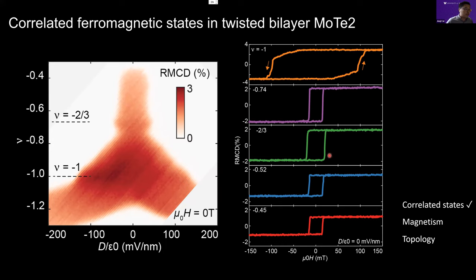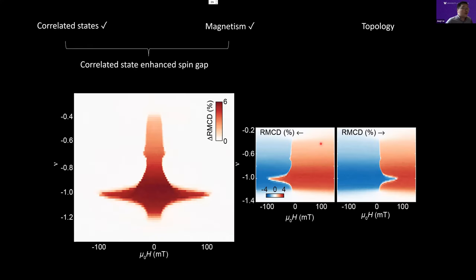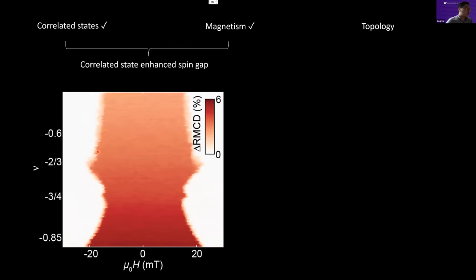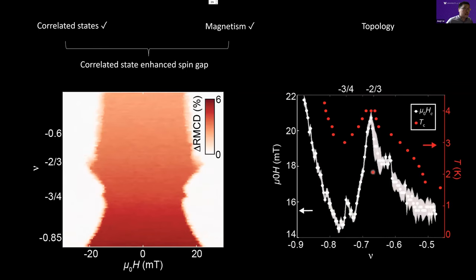What is notable is that the coercive field, which represents the energy you need to pay to flip the magnetic domain, actually increases. Okay, and this is the hallmark of magnetism. So we have established the correlated state and the magnetism in the single system. Now what we want to explore is what these correlated states together with magnetism can give rise to. What we see here is that the correlated state can enhance the spin gap a little bit. If you zoom in on the RMCD scan, you can see that at fractional states the magnetism gets enhanced. And by temperature dependence, you can clearly see that at two-thirds, the magnetism is very strong.